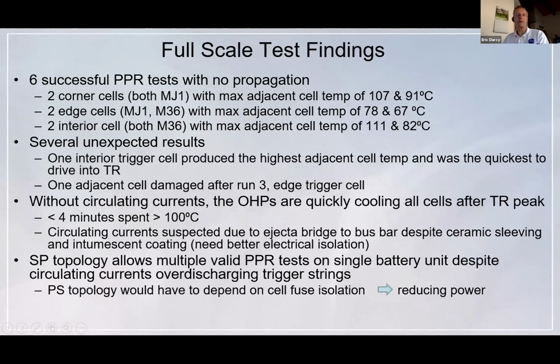We did get one run where we got some circulating currents afterwards. We have a way of protecting against that to improve, but overall that didn't damage the adjacent cells. And overall, our S before P topology provided us with some really good robustness, so that we were able to cycle the battery before and after.